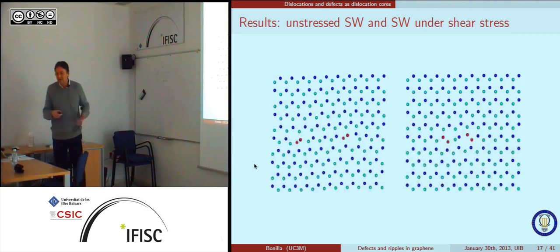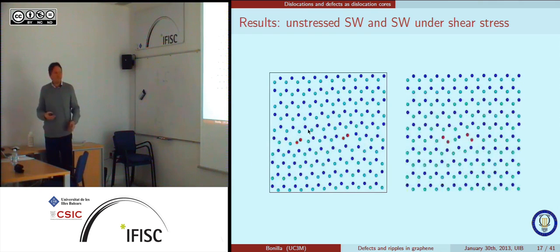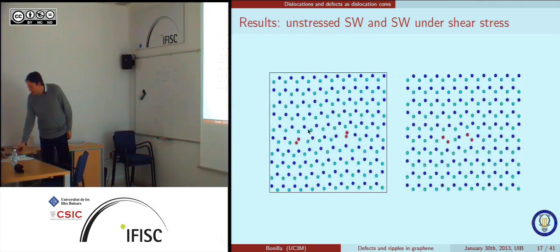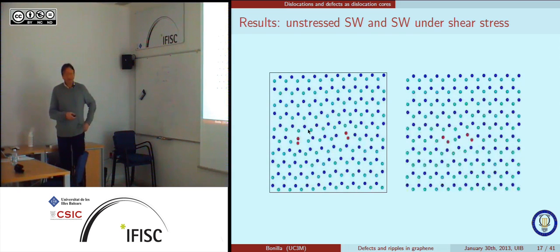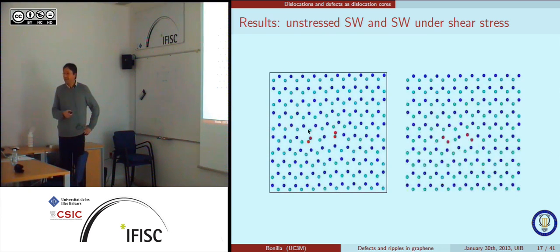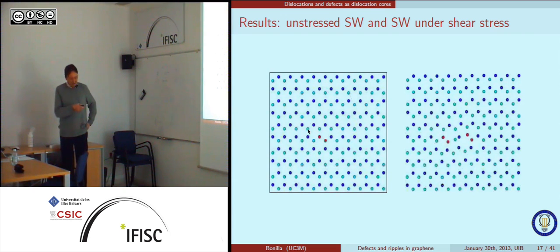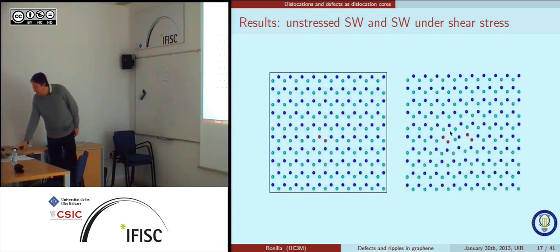This is some of the simulations with the Stone-Wales defect. So we took here two pentagon-heptagon pairs, and we did not apply any external force and released them. And what happens is that, as I said before, they attract each other, and they move around, and if you wait long enough, they reproduce the Stone-Wales defect, and then immediately they disappear. Okay? So this is an example of two dislocations with opposite Burgers vectors, but sharing the same glide line.